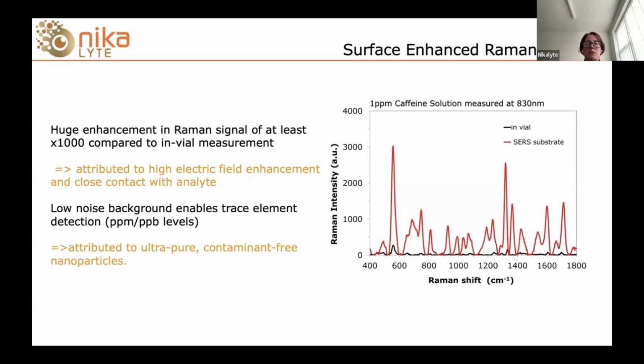The other thing which is really important, and I mentioned this earlier, just so I could bring this up again, is the noise level. So what you can see is these peaks go down to 0 in between the Raman peaks. And that's really important because if you want to distinguish Raman spectra for different molecules, you really need to get rid of the noise. And in fact, part of the power of Raman is really in the database. Without a very good database of clean Raman signals to compare your measured spectra to, it's very difficult to make any sense of Raman signals. So having a clean Raman measurement is very, very important.